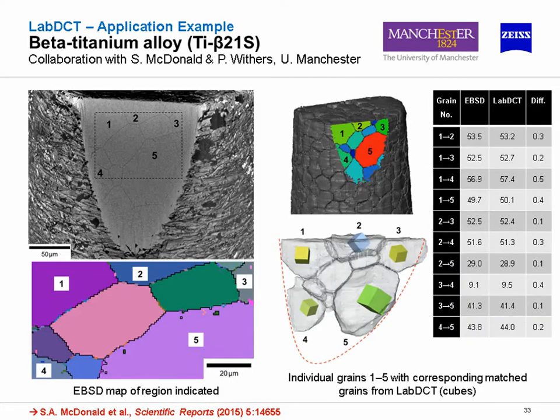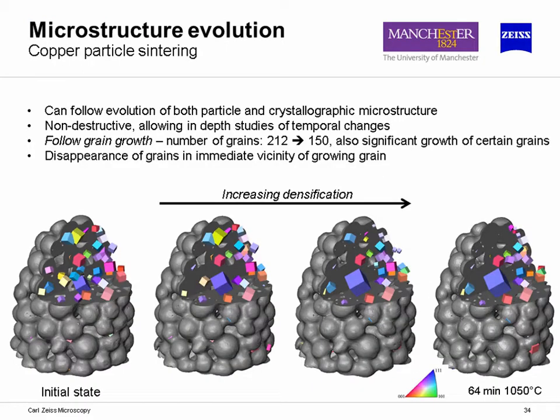Now, this is the first step, that can then be tessellated, for instance, into a structure. But we're working on ways also to extend that morphological analysis into something that looks more EBSD-like. And we've measured this and tested these results against EBSD, against synchrotron-based diffraction contrast tomography, and they agree quite closely. Obviously, EBSD has a finer, higher resolution, which is highly complementary to performing the time-dependent, larger volume study first with the X-ray microscope, and coupling that even to modeling systems or grain growth models. So it was validated against a number of techniques.